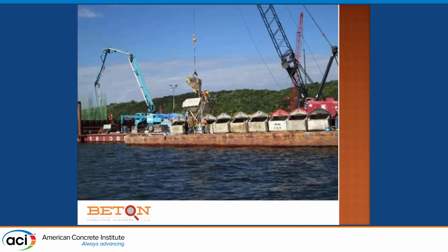So this is what we compromised with, was just having a pump that was, you can see the pump is slightly raised up because it's bolted to that barge and it moves around. And so you're not able to adjust mixes out here if they're starting to need a little bit of superplasticizer. The mixer function in those buckets is pretty bad. As I said, this is the tour company, go on a tour of the construction site.